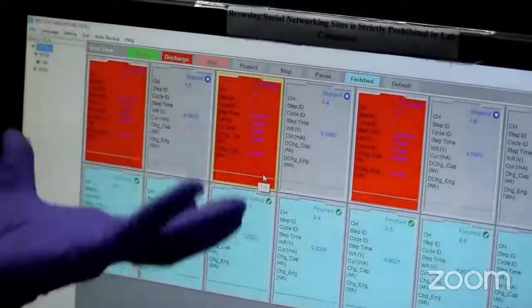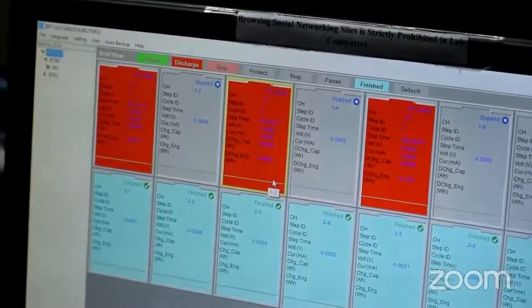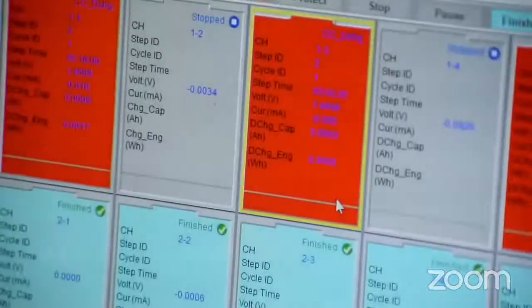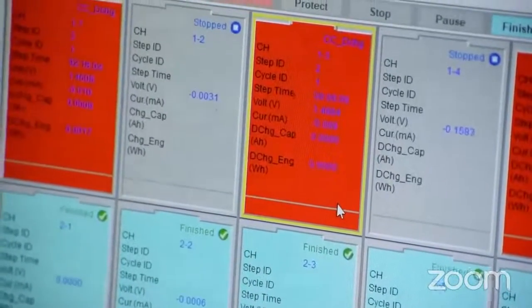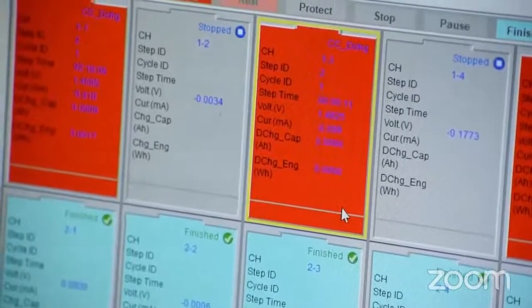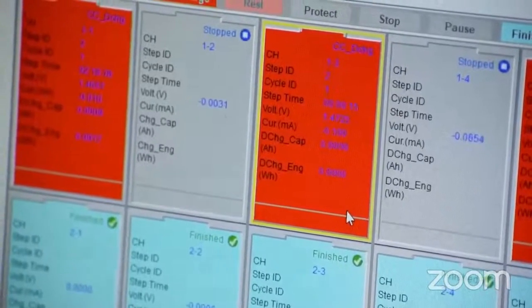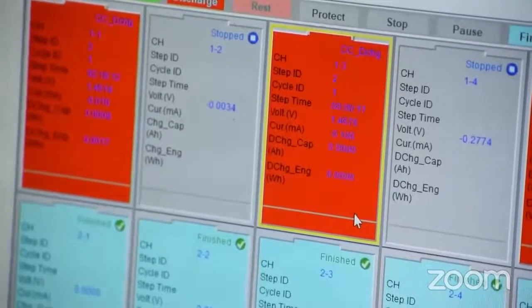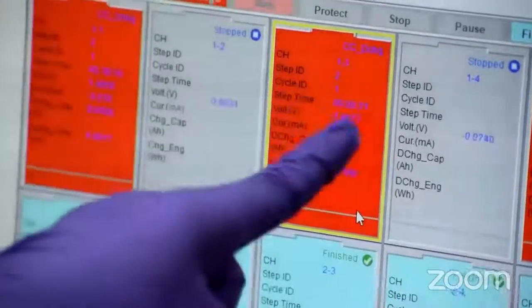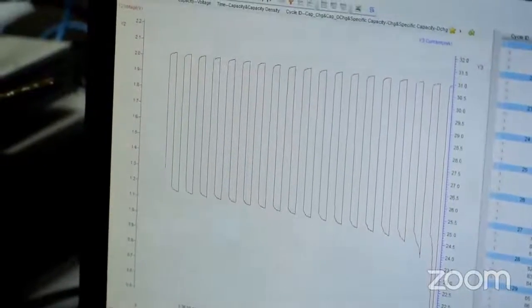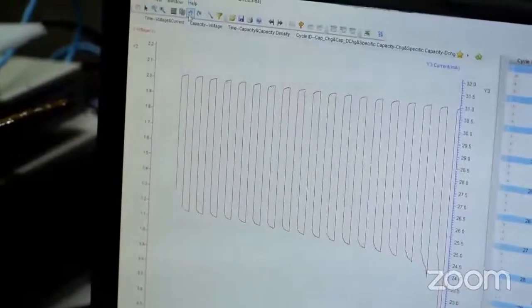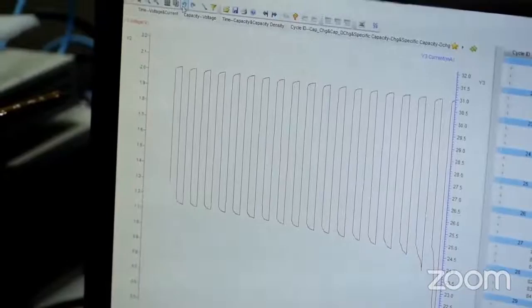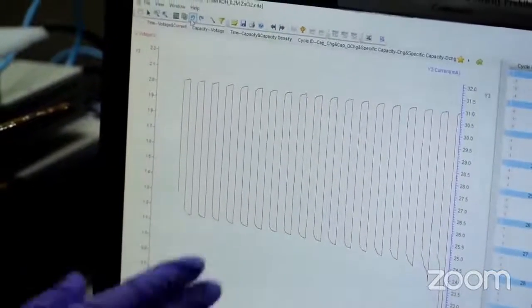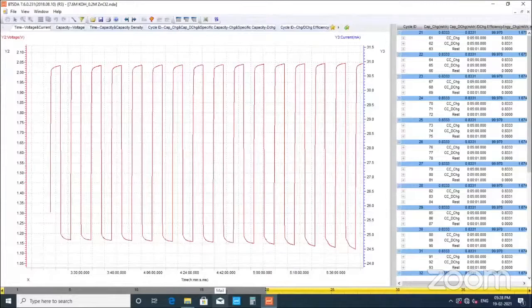We fix a particular current or voltage here and we see the discharge profile or the voltage profile. As you can see here, the cell has started discharging at a constant current. We can calculate the specific capacity as well as the energy density from these values. We can also check the long-term cyclability of our metal-air cells. As you can see here, this cell has run for many cycles.